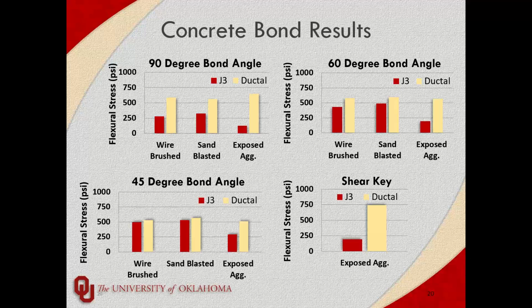One thing to notice, Ductal performed very well in all of the tests. We only had one of the Ductal specimens out of all of the tests that we did that actually failed at the interface, and even it failed at a level similar to the monolithic modulus of rupture of the normal strength concrete. But the rest of them failed in the normal strength concrete, showing very good bond.